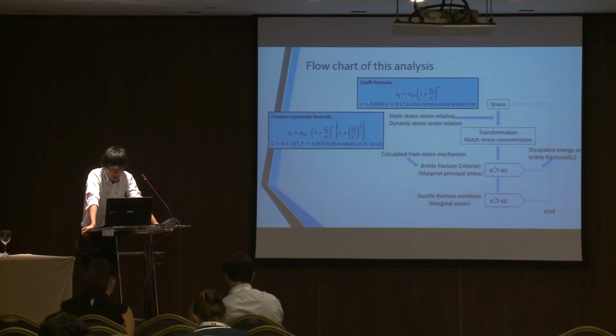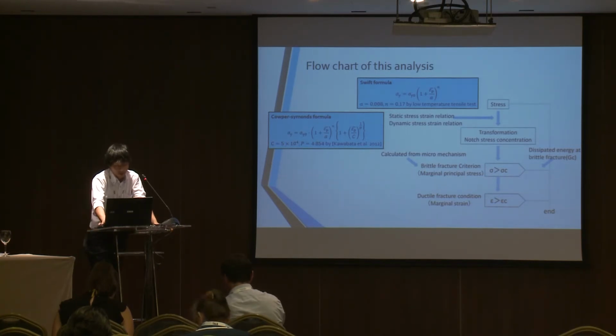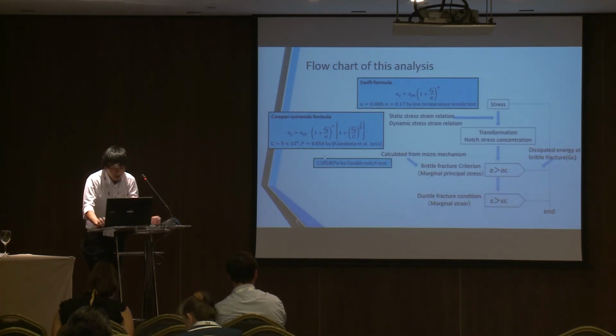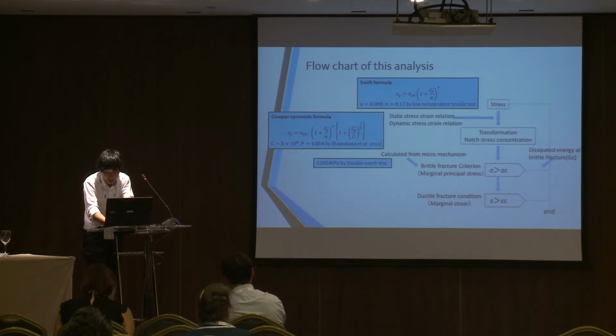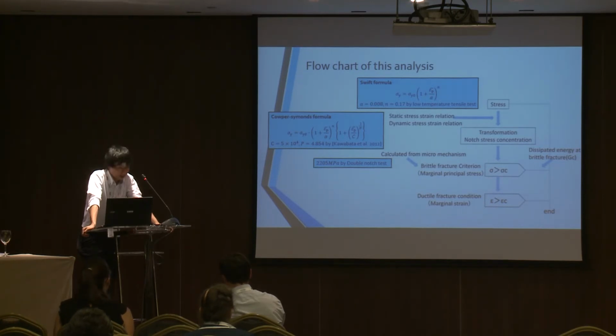The critical principal stress, which is the criterion of brittle fracture, is originally estimated from the microstructure. But in this chapter, the critical principal stress is obtained by separately performing a double notch test for model development. For the critical strain, which is the ductile fracture criterion, the value was determined with reference to the shape of the specimen after the experiment.